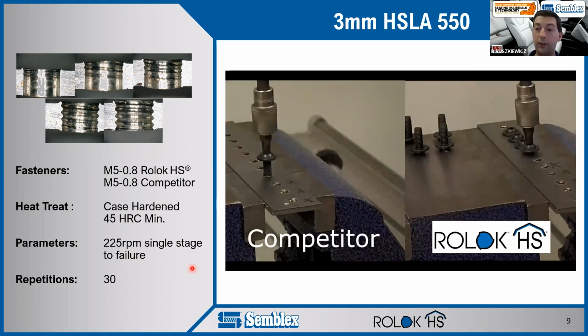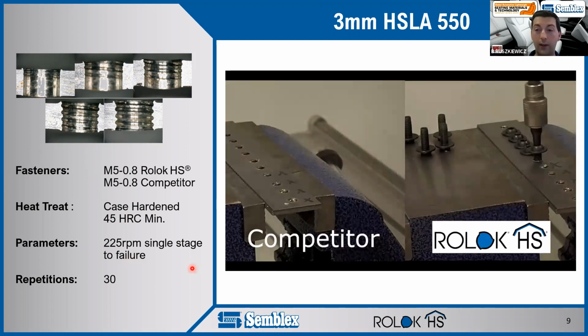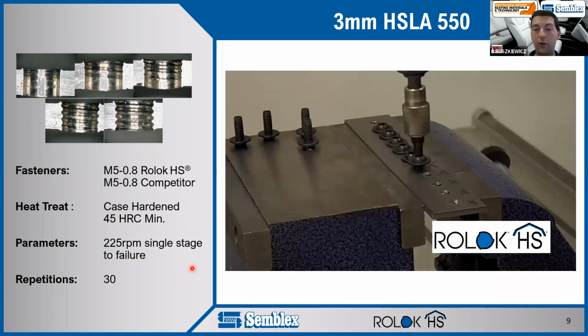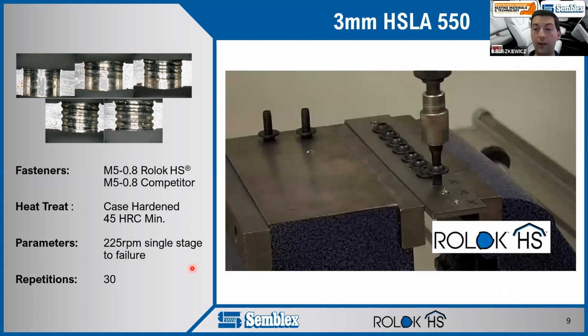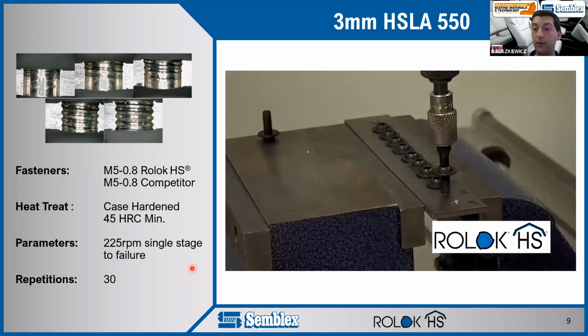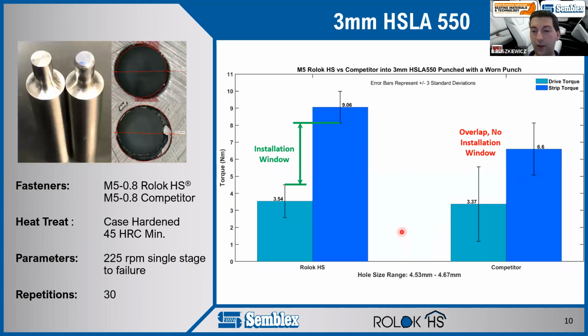So obviously, our customer wanted a solution, so they definitely wanted the data to go with that solution before they went to their own plant trial. To do that, we had to do a couple tricks. The Rolok HS part was able to drive in with 10 pounds of end load, but in order to get drive-to-fail curves for the other part, I needed to push very hard on the fastener. So for the competitor, we increased the end load to about 40 pounds, and that was enough to push the part through. But as you saw in those earlier pictures, we do a lot of damage to the threads when that happens.